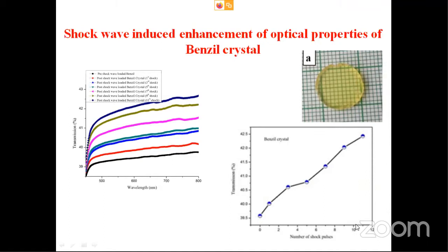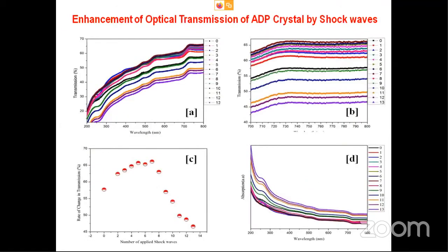This is a way to improve the transparency of the crystal after growing. Generally, by optimizing growth conditions, you can increase the crystalline perfection and the transparency. But in this case, by applying shock waves, you can increase the transparency. This is another one, ADP, which we discussed earlier. We have done the same thing with that one. When we give the shock waves, the transparency is increasing. But after a particular time, it starts to decrease. Up to 6 shocks it increases, then it goes down.